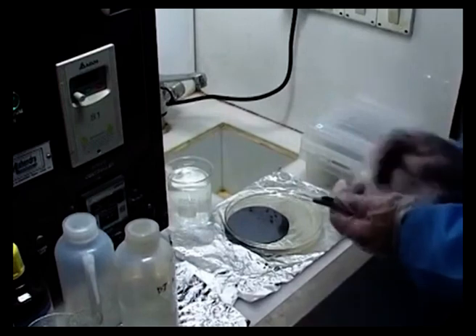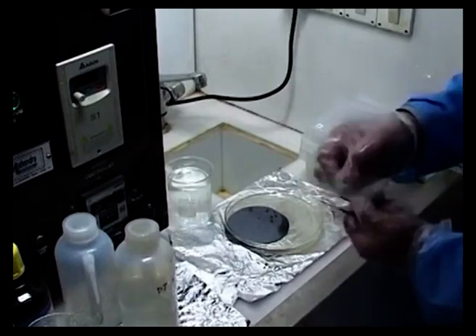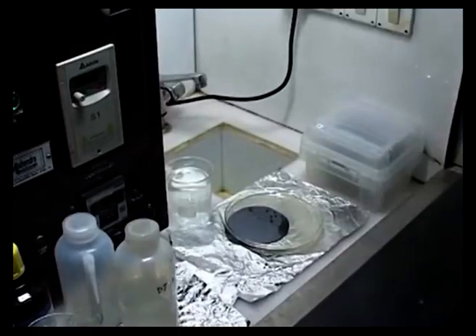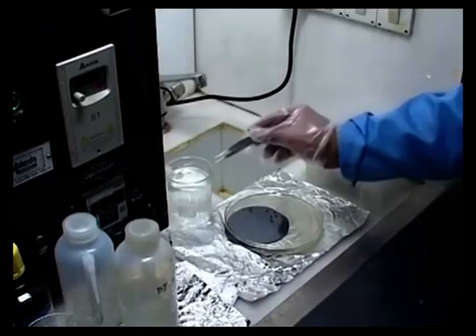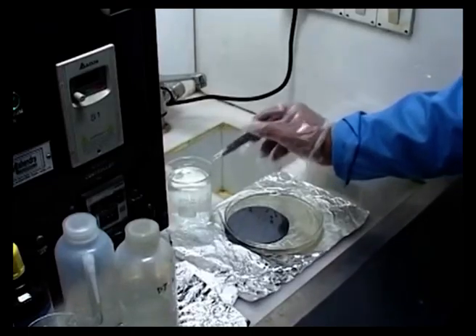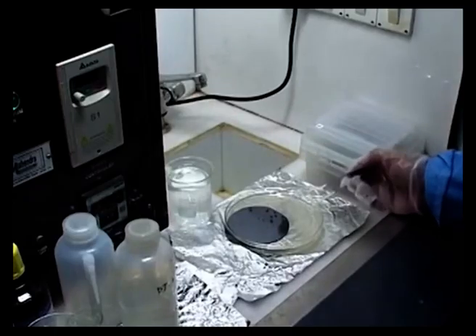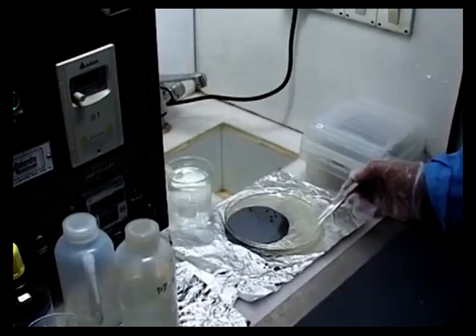So these, as you see, are now Teflon coated. These tweezers have tips which are coated with Teflon, or they can be complete Teflon tweezers which we can use. So what we are going to do is to provide a normal rinsing using distilled water, as you can see here, which is resting in the flask of this particular piranha cleaned wafer sample, and then this would be followed by another wash of deionized water, so that it gives a super clean surface on the wafer.